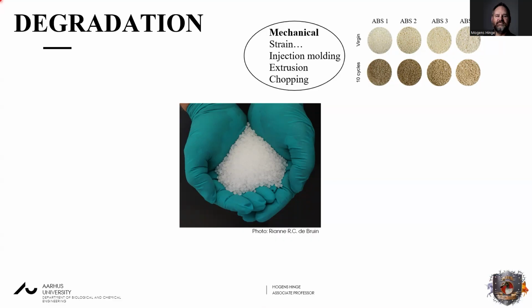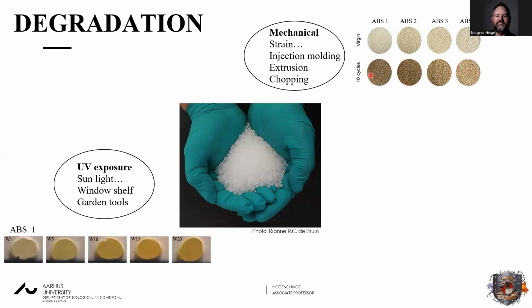This is normally seen in injection molding, in extrusion, in chopping, all processes that are used to reprocess the material. I've taken the different vendors here. So here is how we receive it, the virgin version. And then we have recycled it in an injection molding, chopping, injection molding, chopping cycle. And we've done that 10 times. And it's clear to see that there is a color difference between the different samples here. I'll return to that a bit later.